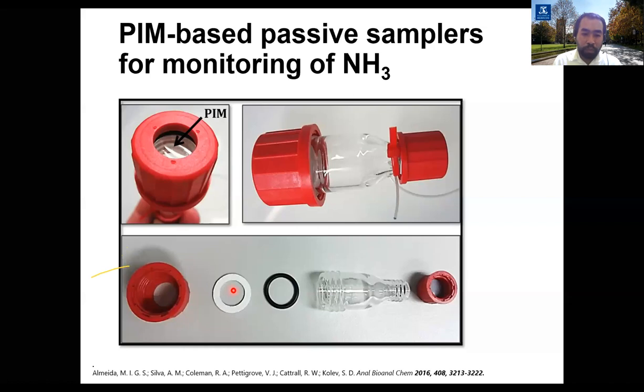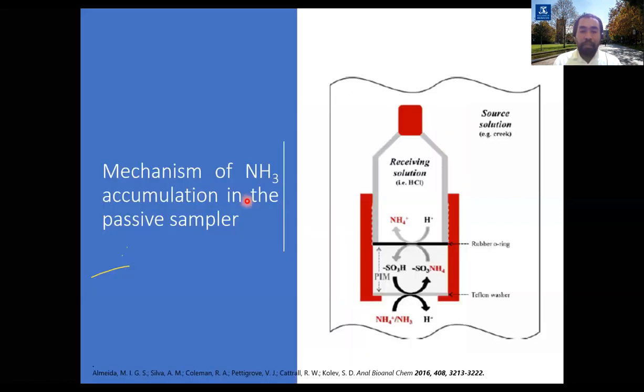Basically, we place the membrane between the Teflon washer and an O-ring. We place it into the cap with aperture before we screw in the glass vessel. And then we insert the receiving solution into our passive sampling device. This slide shows the mechanism of how ammonia is accumulated in our passive sampler. Again, because the extractant used is a cationic exchanger, the ammonium will be protonated and bind to the cationic exchanger, and then the complex will diffuse to the other side of the membrane, where the ammonia is back-extracted in exchange with a proton.